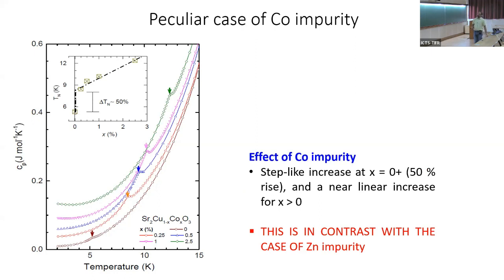So here we show the specific heat as a function of temperature for various cobalt dopings. And you see that as you increase the cobalt concentration, the temperature, so this is for the linear chain, first of all, because now we want to understand what cobalt is doing. Therefore, we will not touch the messy system, which is the zigzag system, where there are 3 interactions to deal with. So we go back to the linear chain system where there are only 2 interactions, and we see that the pristine sample orders at some temperature near 5 Kelvin, and then this is how the ordering temperature evolves.